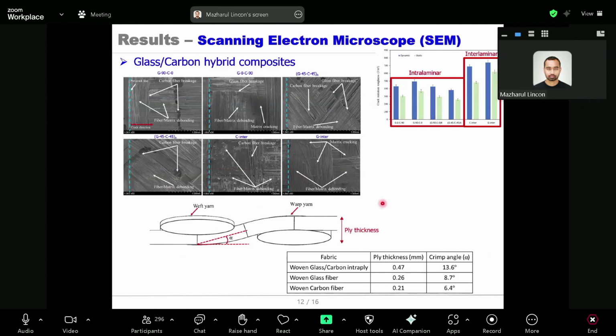Now, the intralaminar hybrid composite is thicker, that's why it shows a high crimp angle. From the literature, we know that a high crimp angle creates a jamming effect for the propagation of strength across the fiber, which reduces the fabric's breaking strength. As the intralaminar hybrid composites have a high crimp angle, they have less fabric strength. That's why they show low fracture initiation toughness compared to interlaminar hybrid composites.